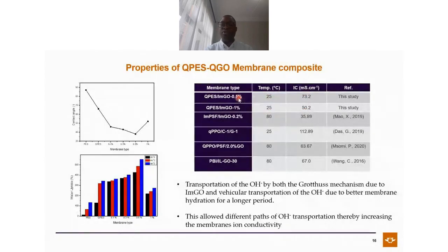You look at the one with 0.5, it had about 73. The one with 1% had about 50. When you look at the one with 73 and you compare it to the rest of the material, you can see that it's still one of the highest. This one, which is quaternized, had about 112. They also did exactly the same thing that we did. They quaternized the membrane, they also quaternized the filler, which is why they're getting about 112 in terms of ion conductivity. So what are we saying?